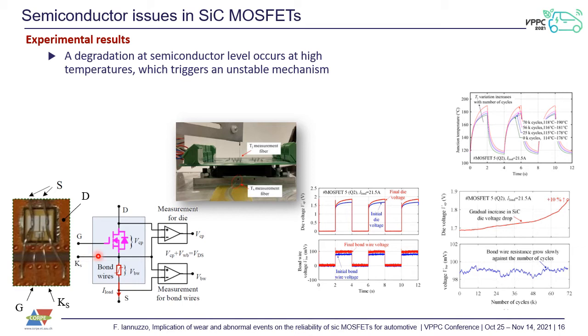Again, we measure the junction temperature through optical fibers, as in the picture here, and here you can see some results during power cycling. Now the interesting thing is that in the beginning of power cycling, at pristine condition, the on-state voltage drop looked like this. You can see the blue curve here, but after power cycling, at the end of life, the on-state voltage drop had increased up to the red curve.